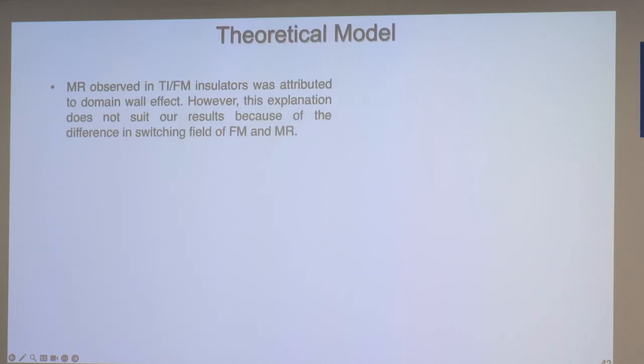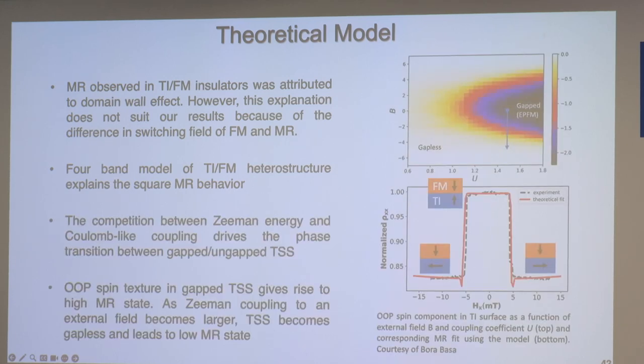Okay. So we worked with Matthew Gilbert's group on a theoretical model. This model was basically very similar to the model that they created for the YIG, looking at switching of one layer on top of the other, sort of like a spin valve type effect. This clearly wasn't a domain wall effect. It looks something more like a spin valve type effect. The only complication here is that this sort of spin valve effect explains the in-plane field switching, but not the out-of-plane field switching. And so, the other thing that could happen if you have switching that occurs in all three field directions, that could be due to something like skyrmions, which don't care about the field direction. They have their own structure, or something more exotic like that. And so that's the sort of thing that we have no actual basis for, but at least it's consistent with what we see and that we're looking at more now.